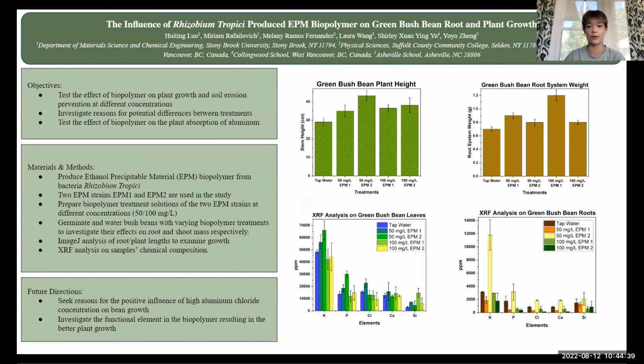From the data, we find out that all the biopolymer treated groups have a higher mean stem heights than the tap water control group. There is a significant difference between the control and the 50 milligram per liter EPM2 treatment group. The 95% confidence interval indicates that the difference of the mean stem heights of the two groups lies between 7 centimeters to 18 centimeters.